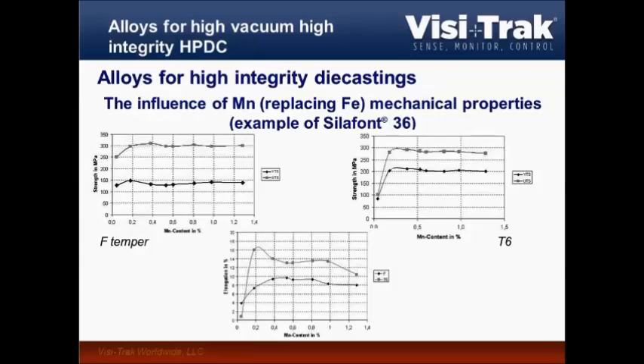Now we have seen before the sludge factor is 1 times iron plus 2 times manganese. So the more manganese I have in there, the more sensitive my alloy will become to sludge particle creation. So that is clearly the objective, and that was one reason why the Aural 2 alloy works with a slightly higher iron content, which was found does not harm the properties. It works with 0.2, sometimes even 0.25, and then lowered the manganese content to only 0.4, 0.5%.